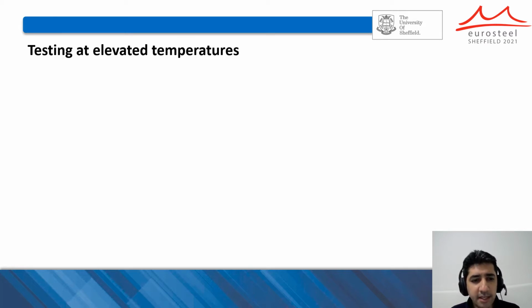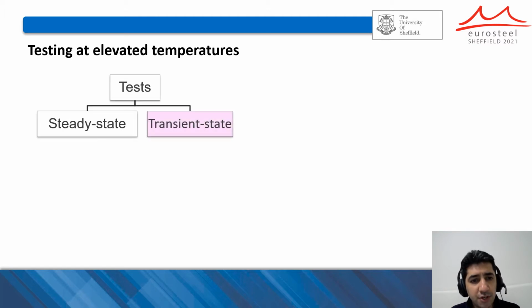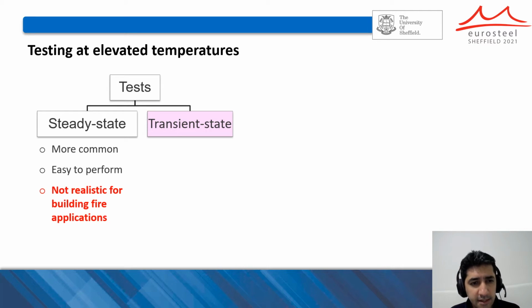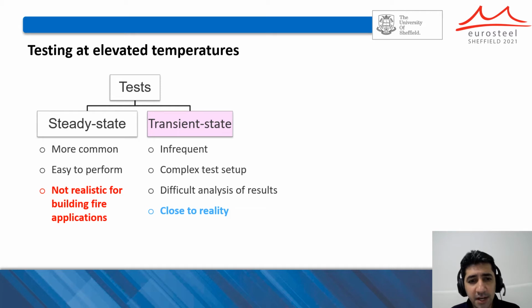When it comes to testing at elevated temperatures, we have two major approaches: steady-state test and transient-state test. Steady-state tests are more common and easier to perform, but as the tests are performed under constant temperature conditions, they cannot realistically simulate the real structural fire or the real building fire. So, for this purpose, transient state tests are preferred.